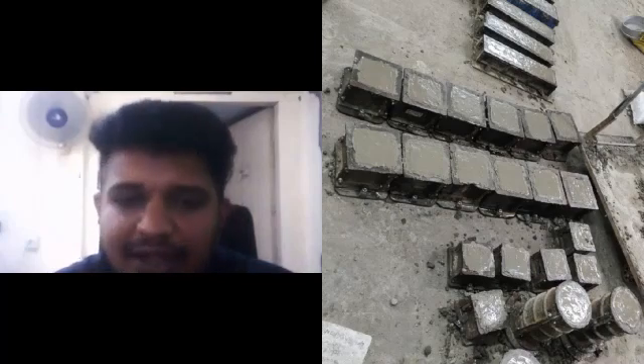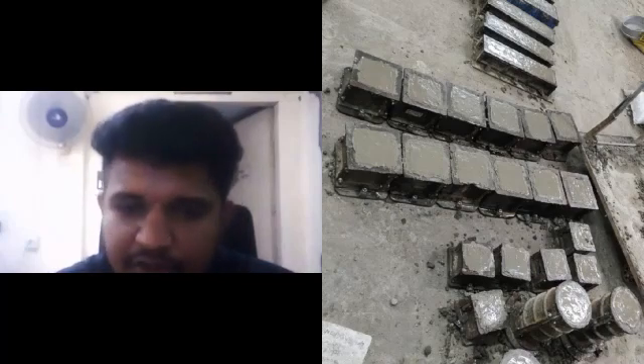One was carried out at Dhariwal power plant in Chandrapur. It's a thermal power station, and they laid a 500-meter stretch of PQC, pavement quality concrete road, with 100% replacement of sand with bottom ash. Past studies in the area have suggested using fly ash, but this much quantity of bottom ash per cubic meter of concrete was never reported in previous research.